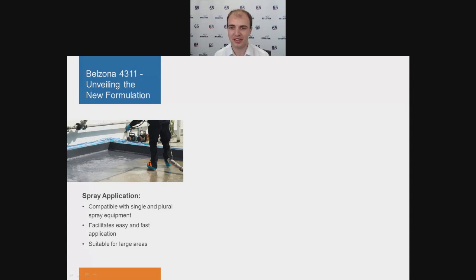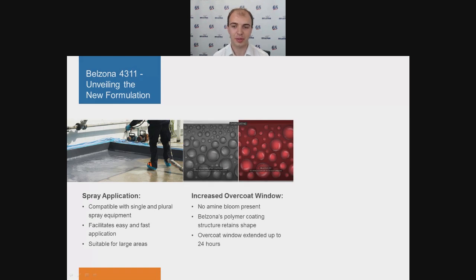So, as the video alluded to, the addition of being sprayable is one of the application upgrades for this system. Formerly, it was just hand applied, but now it can be compatible with airless, single and plural spray equipment, which aids faster application, especially over large areas. Now, this goes hand in hand with the coating having an increased overcoat window. So it's been extended up to 24 hours and will not experience any of the negative effects associated with amine bloom, such as the loss of intercoat adhesion seen on standard epoxy coatings. And overall, this just aids a fast back to service time.